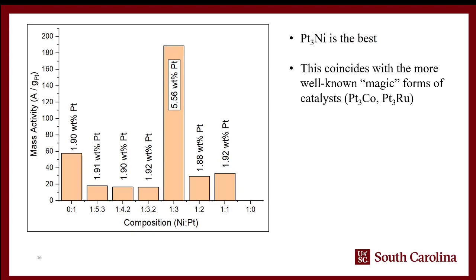And so what's interesting is that for the cobalt, it was platinum 3 cobalt. Here we see platinum 3 nickel, and this coincides with the more well-known, quote-unquote, magic forms of catalysts. There's been a lot of work done with the oxygen reduction reaction where multiple groups have found that platinum 3 with some metal, a lot of times something like cobalt, is more active than just pure platinum. And I don't know that anybody's really got a good explanation for it at this point, aside from the secondary metal acting as some kind of assistance to improve turnover at the main catalyst site. But we did see that here with the nickel, but not with the cobalt, which was kind of interesting. One of them was sort of the magic form, one was not.